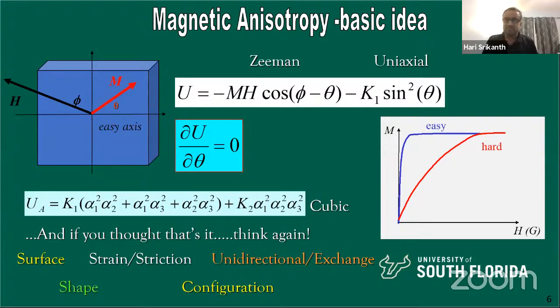Well, this is just the first quadrant, right? If you do the full loop, then you can see the hysteresis loop, which looks very similar to the ferroelectric hysteresis that many of you are familiar with and probably heard about, saw a lot of them in this conference. Okay, so now the uniaxial term is simply saying that you do have a preferred direction. You can actually include the preferred directions. You can take other contributions such as cubic anisotropy. However, when it comes to nanoparticles, there are many terms that can contribute to the anisotropy, okay?